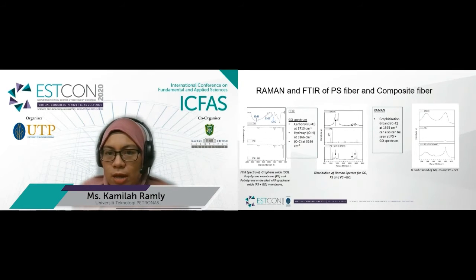Infrared is excellent for carbonyl C=O species, while Raman is quite variable. This band is easily identified in the IR spectrum because of its intensity and lack of interference from most other group frequencies. The carbonyl in graphene oxide can be seen at wave number 1713. In addition to that, the characteristic peaks of hydroxyl OH stretching at 3166 and the C=C can also be seen at 1586.